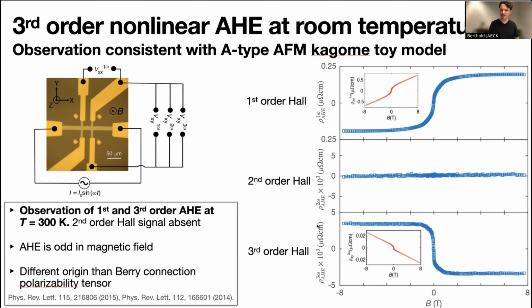We also find that the third order response is odd in magnetic field, meaning it's zero at zero magnetic field. This is important because a third order anomalous Hall effect has been observed before, induced by the Berry connection polarizability tensor. However, that one is even in magnetic field and therefore can be distinguished from our observation.